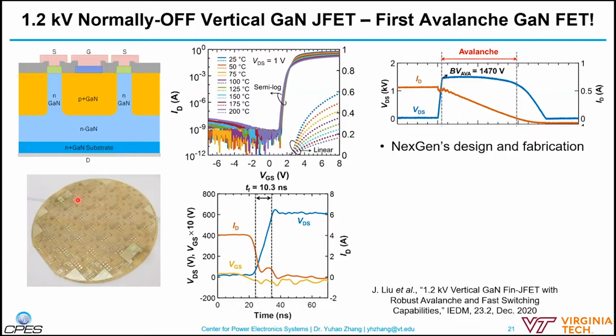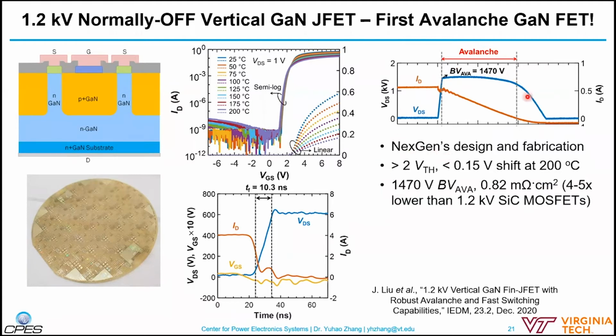These are large-area devices on a 4-inch GaN substrate. Looking at the transfer characteristics, up to 200 degrees C, the threshold voltage is very stable. It also realized avalanche. That's the first demonstration of avalanche capability in GaN transistors, a textbook avalanche test in a circuit test in my lab. And the specific on-resistance is about 4 to 5 times lower than the state-of-the-art commercial 1.2 kV silicon carbide MOSFET.